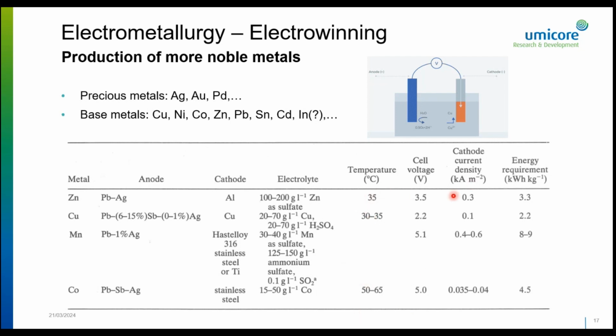What you also see is the current densities are much lower than the ones indicated for molten salt electrolysis. So this is the downside of electrowinning in aqueous media, that the current densities are much lower. As something I didn't mention, as you use electrons to reduce a metal, the metal production is directly correlated to the current density. So what you want is to maximize the production capacity of your installation. So you want to maximize the current density at which you work. And for electrowinning, you're limited to do that in aqueous media. For the molten salt electrolysis, you can go to very high current densities.